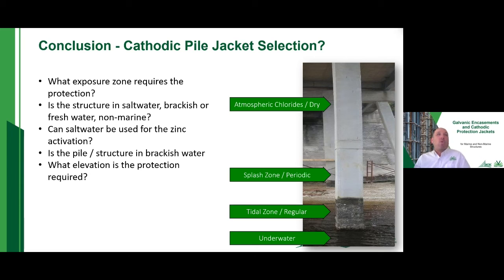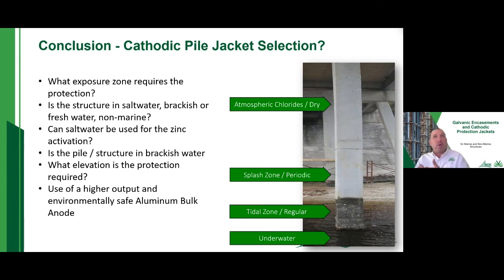Can we use salt water? If you can use salt water in this environment, you're going to use a Tidal Plus jacket. It's going to rely on the salt water to activate the zinc. As you move higher up, obviously you're going to have to go to an activated system because you don't have the salt water available. And everything under the water, we're using aluminum bulk anodes as well.